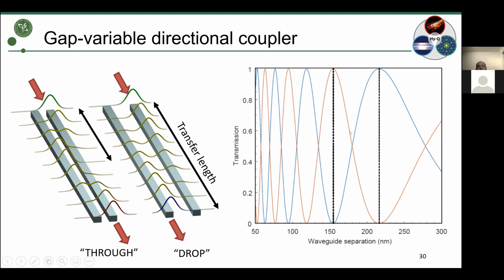This is just a simulation that shows, as a function of the waveguide separation, how much intensity is being transferred to one port or to the other. And you can see how strong this effect becomes when you come to very, very small distances, like you're coming to the 50, 60 nanometer distance, and just 10 nanometer motion is enough to switch light completely from one side to the other. It's actually quite impressive.